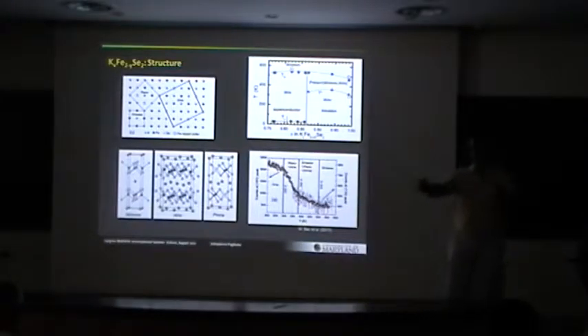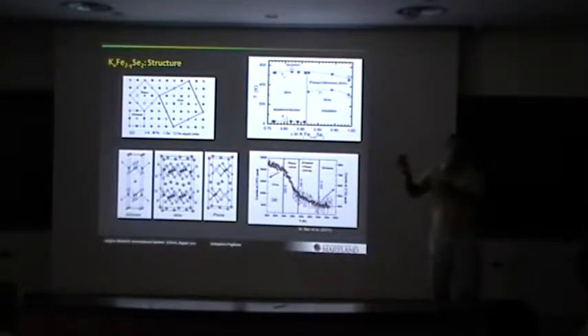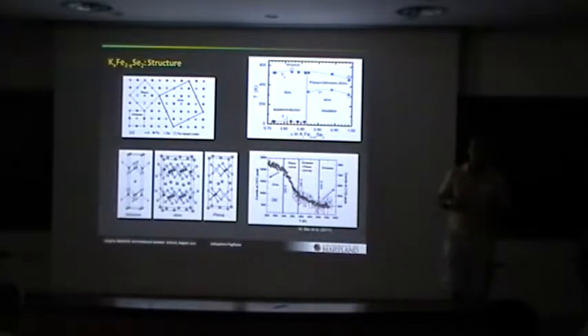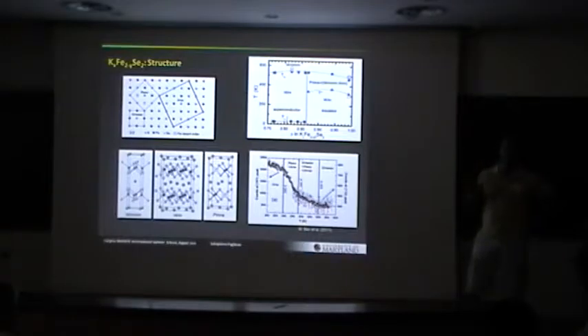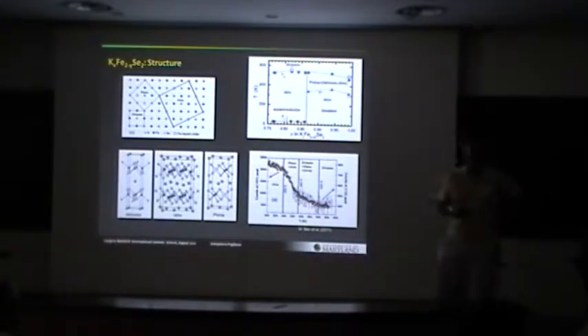You have ordered vacancies. You can imagine if you heat it up and you quench it down really quickly, the vacancies may be disordered. And I'm still not clear as to how that relates with Tc and so on, whether the superconductivity appears or not. If I remember correctly, I think the vacancies have to be ordered in order to see superconductivity. No, it's the other way around. At least that's the claim.